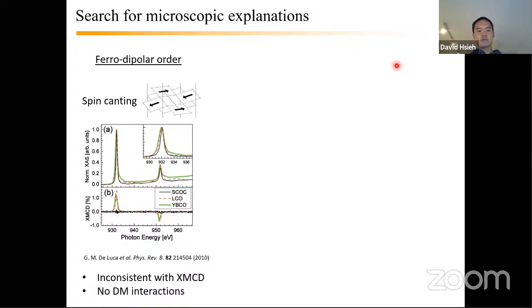This material is crystallographically quite perfect. There are no known distortions that would lead to any Dzyaloshinskii-Moriya interactions that would cause such canting. There have been some X-ray magnetic circular dichroism experiments performed on this compound, in comparison to other compounds like LCO or YBCO where there's known canting, and there's no detectable spin canting in SCOC, again consistent with the lack of DM interaction. Here you can see in LCO, the canting is just a few degrees, 2 or 3 degrees, which they pick up as this red curve, whereas SCOC is really zero, at least within their measurement noise. So we don't think it's spin canting.